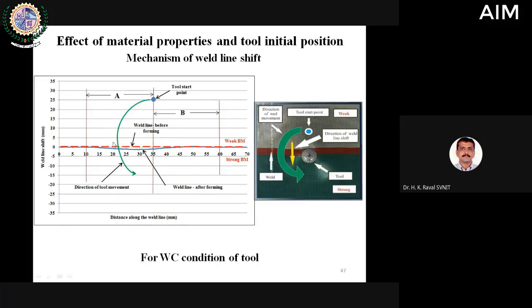Now, in this activity, the tool is moving from weak to strong, and even in the stamping operation, when you perform the stamping, the weld line will shift towards the stronger material because weaker material is forming more than stronger material. So the weld line always shifts towards the stronger material. The same is observed here, but you can see the deformation is much more in this area. Displacement is not much in this area. It is more because there are two different phenomena acting here. Weld line shift is due to the combination of weaker and stronger material. Weaker material will have more deformation than stronger material. So that will result in the weld line shift towards stronger material.